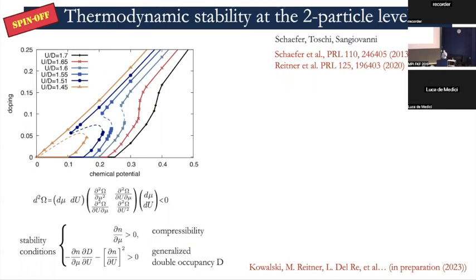Now, what would be nice is, instead of analyzing all these derivatives, to have a local criterion to know if the solution is stable or unstable. And this is exactly what comes out by analyzing this quantity that was studied along these years by Thomas, by Giorgio and Alessandro. I will signal this is also the work of Matthias Reitner and Lorenzo Del Re, and there is a nice poster where these calculations are shown in more detail. So I urge you to go look at that.